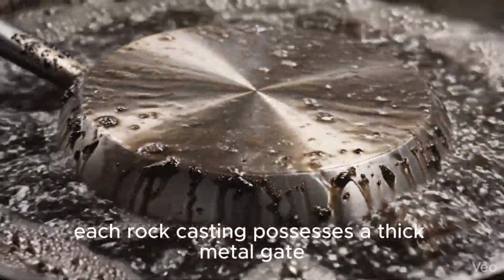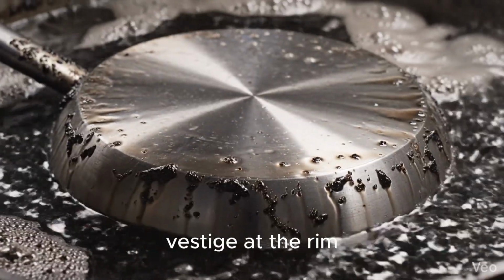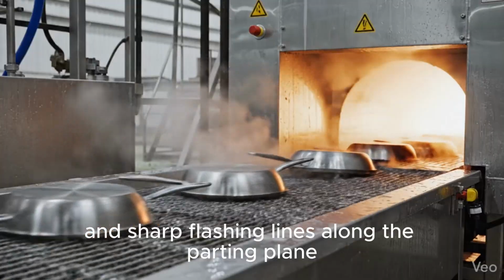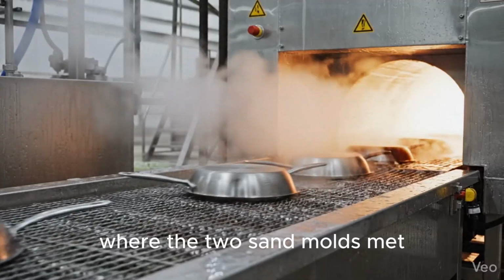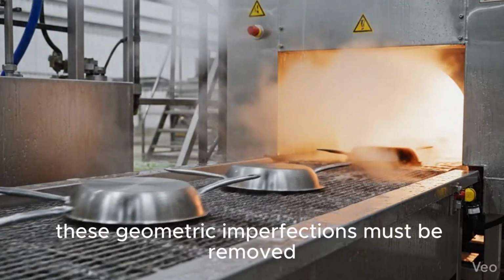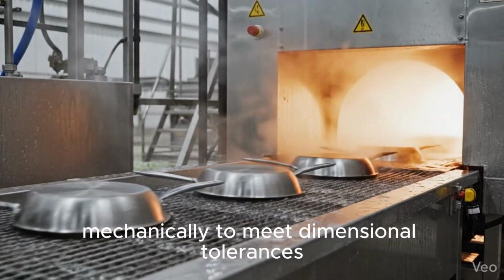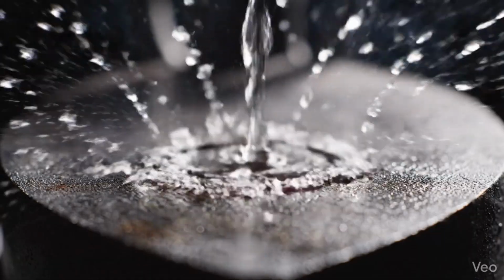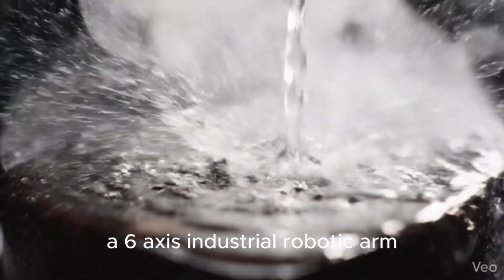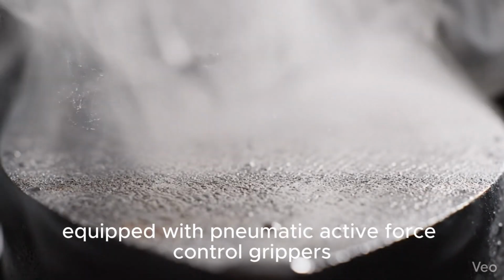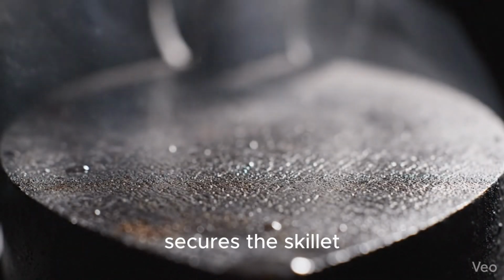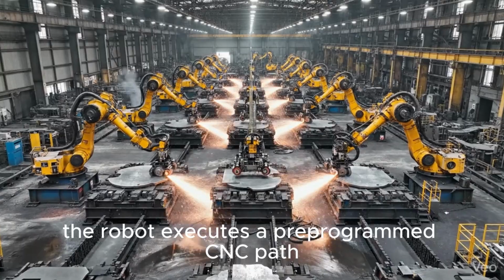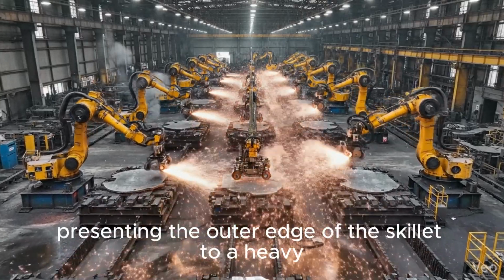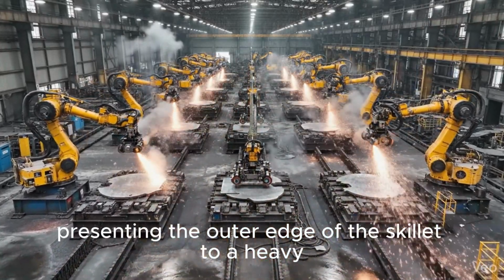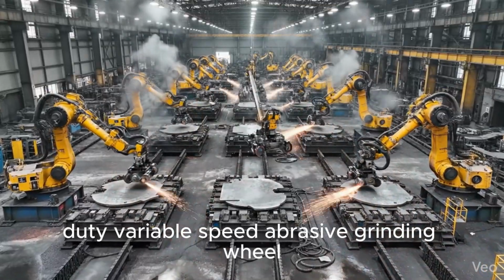Each raw casting possesses a thick metal gate vestige at the rim and sharp flashing lines along the parting plane where the two sand molds met. These geometric imperfections must be removed mechanically to meet dimensional tolerances. A 6-axis industrial robotic arm equipped with pneumatic active force-controlled grippers secures the skillet. The robot executes a pre-programmed CNC path, presenting the outer edge of the skillet to a heavy-duty, variable-speed abrasive grinding